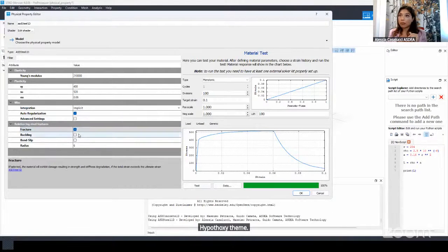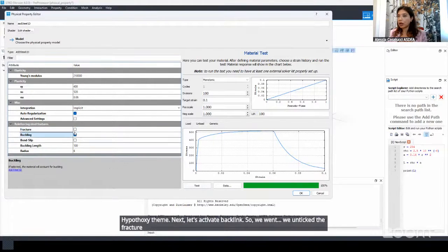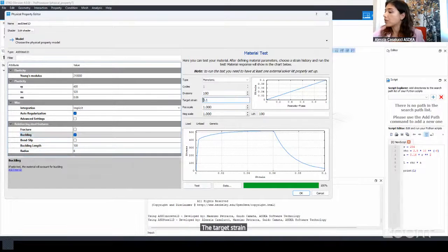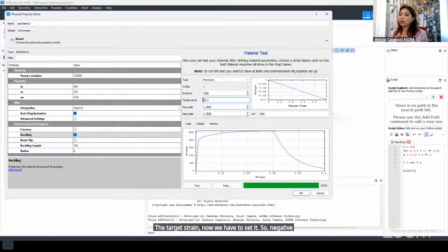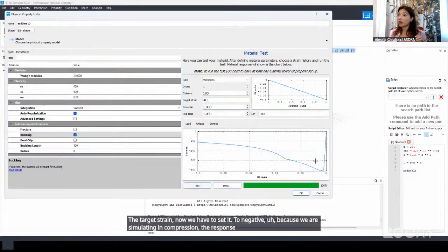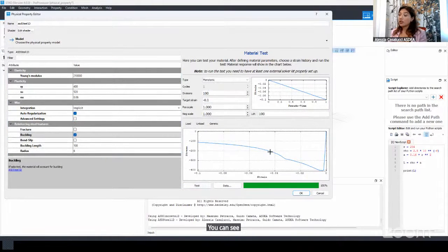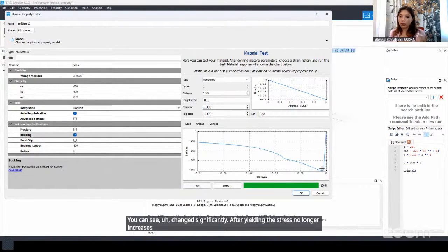Next, let's activate buckling. So we untick the fracture and we take buckling instead. In this case, it's not enough to provide just the radius. You also need to specify the buckling length. You'll notice that the target strain, now we have to set it to negative because we are simulating in compression. The response curve, you could see, changed significantly. After yielding, the stress no longer increases linearly or plateaus. Instead, it drops progressively, and this reflects the loss of actual stiffness due to buckling, which becomes more pronounced as the strain increases.